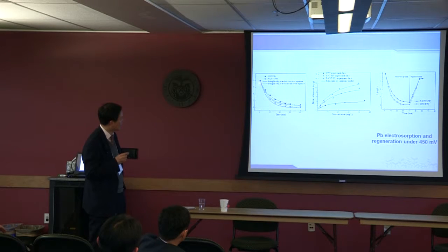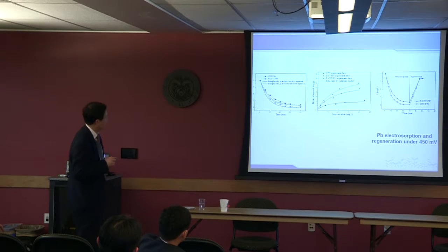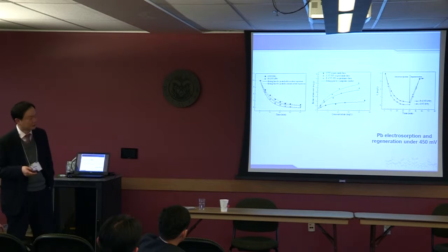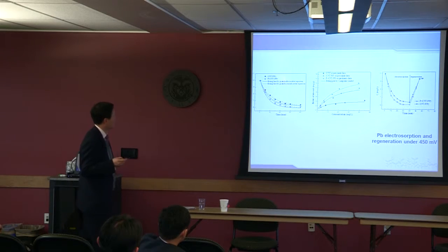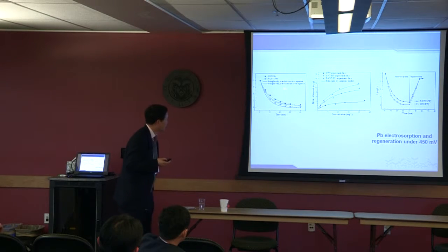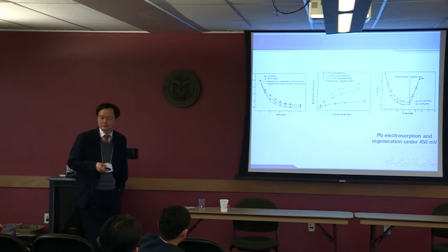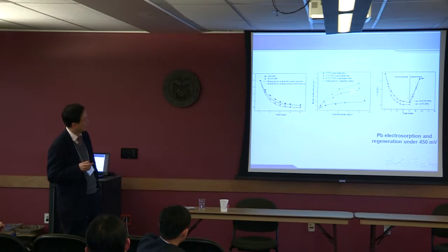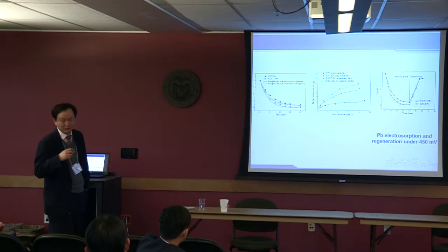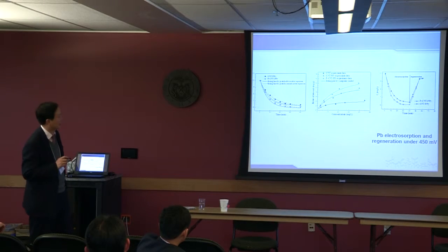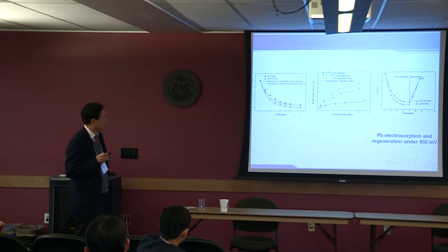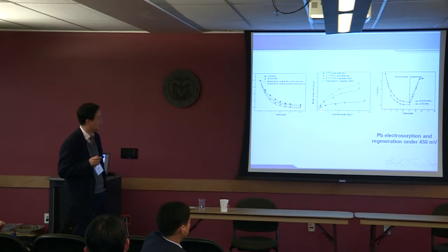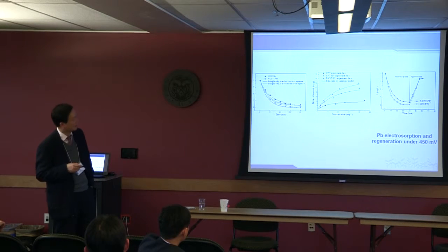From this diagram, we did the regressions, which show that the kinetics follows the pseudo second order kinetics model. This one shows which isotherm can fit the data, and we found that the Langmuir isotherm fits the data much better than the others.